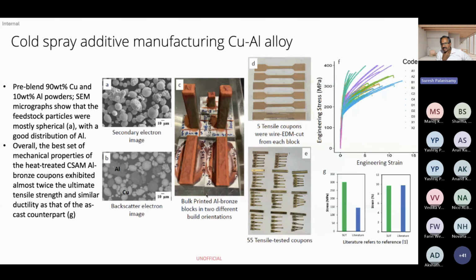Another important critical factor is reproducibility and repeatability. That's why we've done extensive studies. As you can see, 55 tensile-tested coupons were studied, and how much better properties are achieved over a period of time is very important. That is one of the limitations of additive manufacturing, I would say. The powder particles also vary, which might change the properties. So you always have to make sure that reproducibility and repeatability are happening up to a certain level.